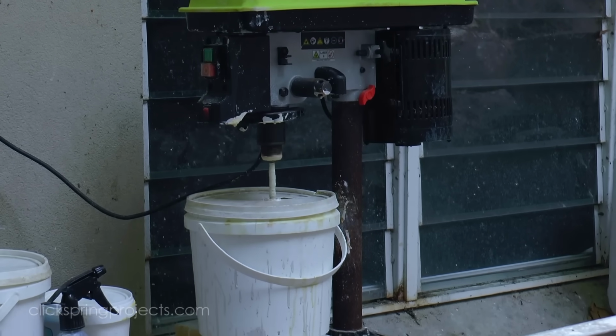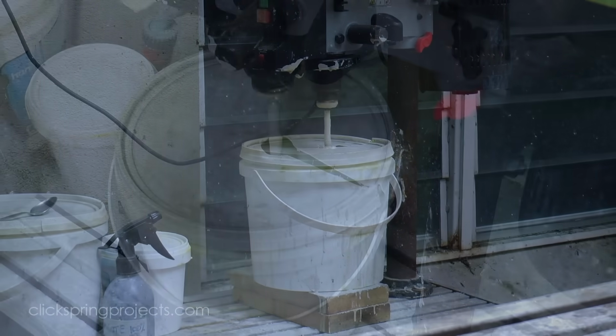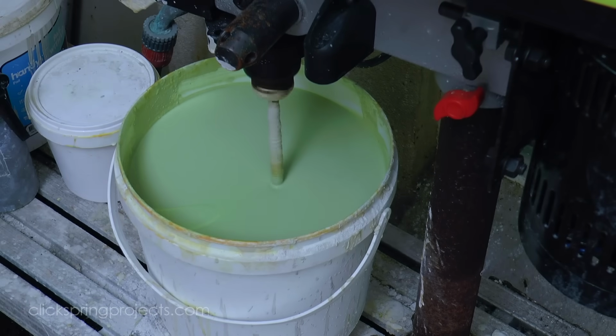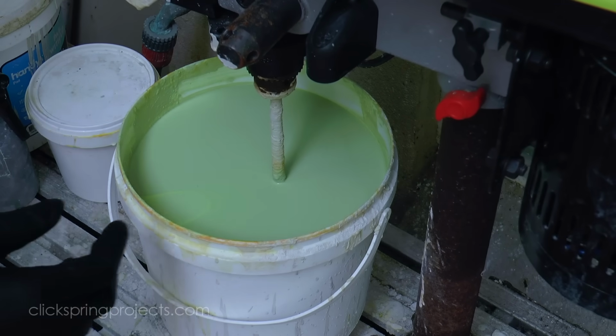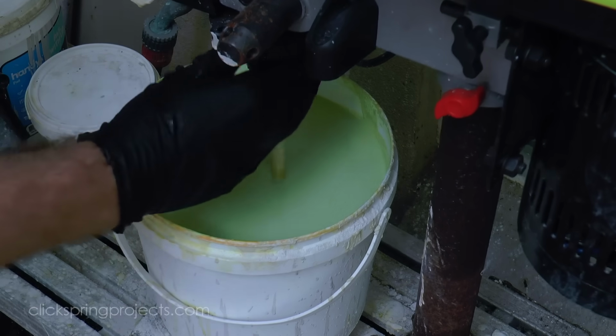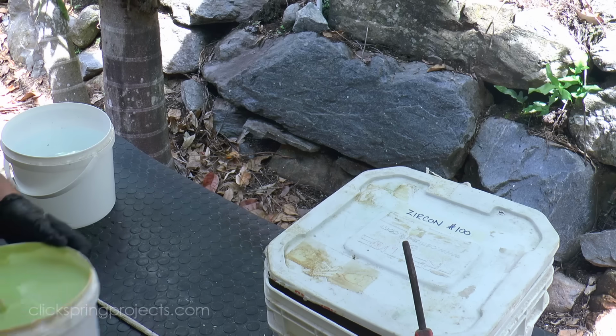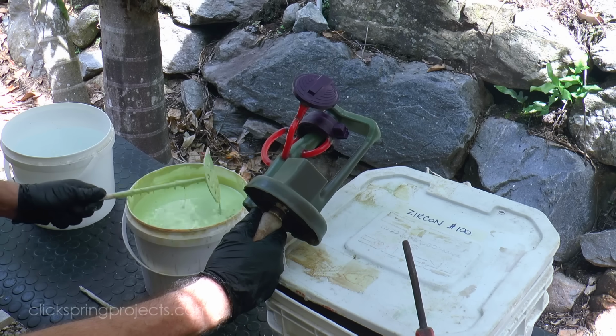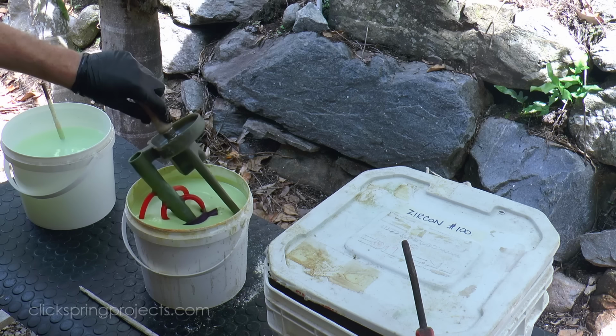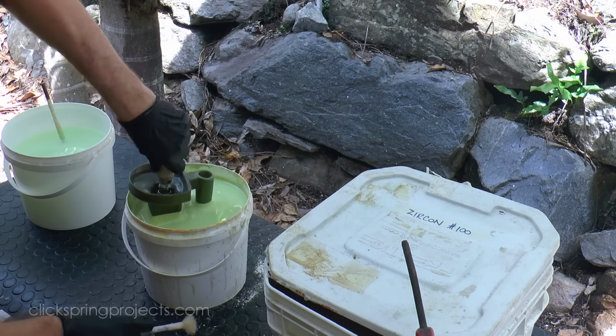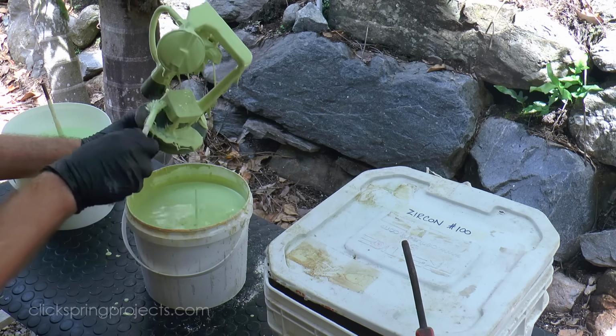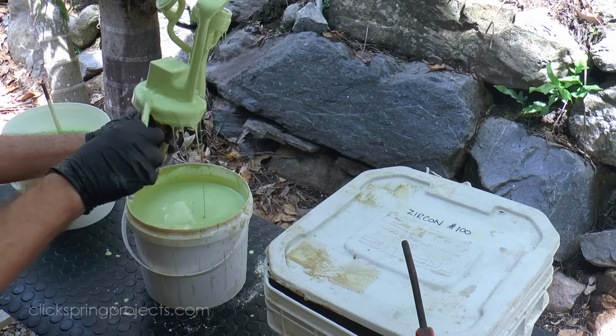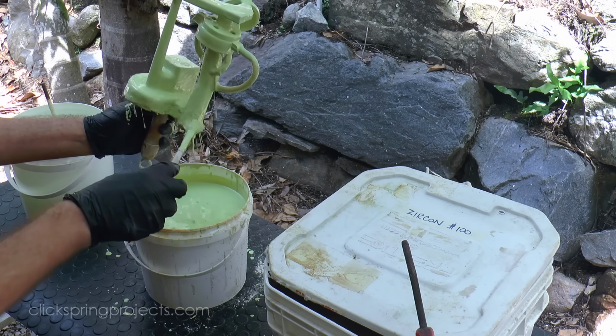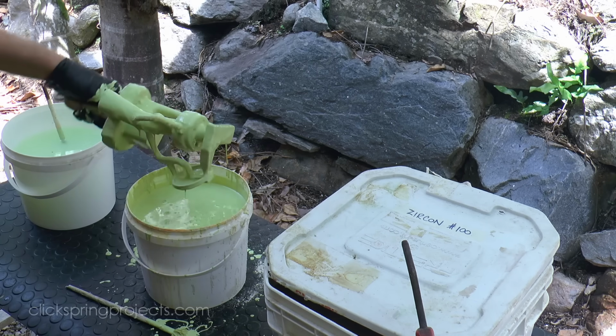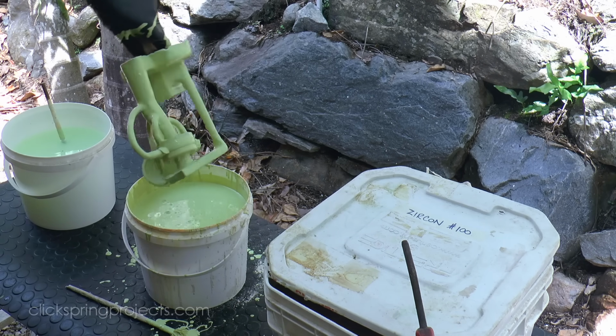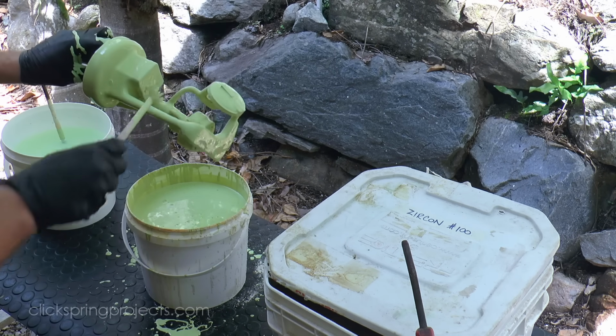The investment process benefits greatly from being conducted as a standardised routine to help achieve consistency across all layers. My routine is to first resuspend the slurry and then position it alongside the sand that I'm about to apply, along with a wash bucket and a source of compressed air. The pattern is slowly dipped into the slurry, and a brush serves to help cover any sections missed in the dip. A brush can also help push the slurry into any deeper cavities in the pattern and remove surface bubbles.